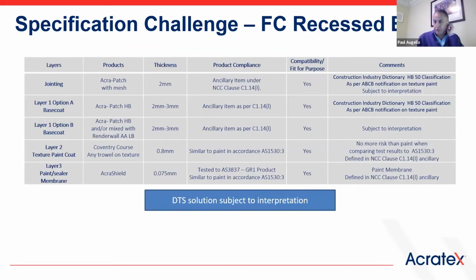The next one is fibre cement sheet, and this has probably been the more challenging one. There are two types of fibre cement sheet: a recessed edge and an express jointed one. If you look at the recessed edge one, which has been more commonly used, there's a jointing compound that goes to the joint first. That, in our view, is a paint texture, and that's required with a mesh in it again for the joint elements. You've got a levelling coat that's generally applied to 2 to 3 millimetres, which is premix as well.